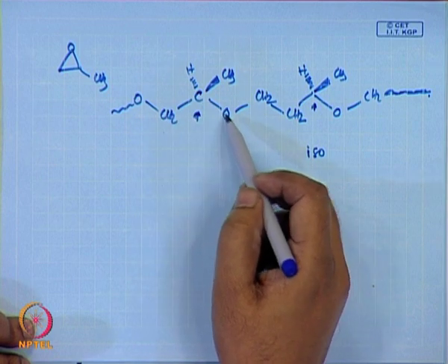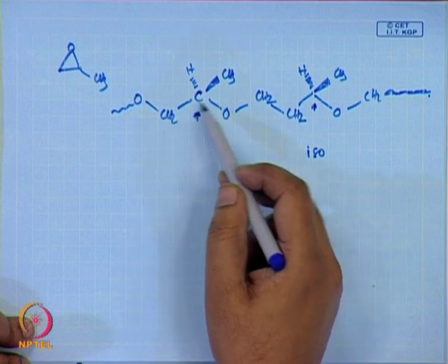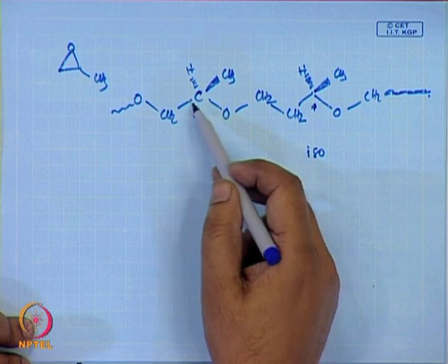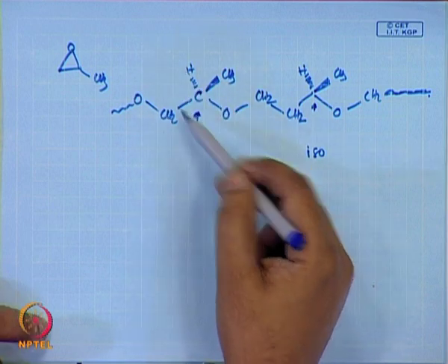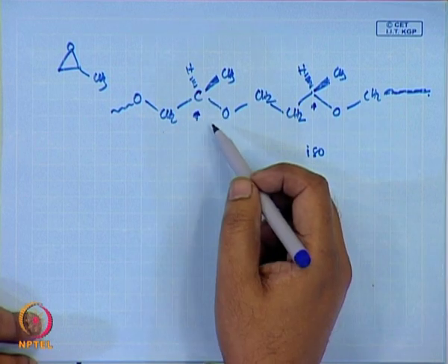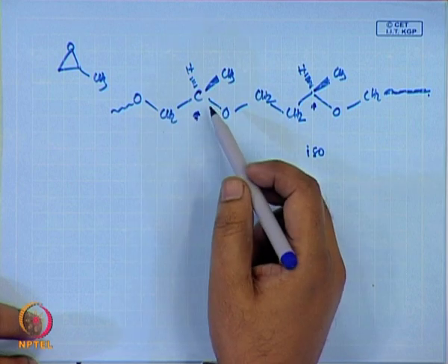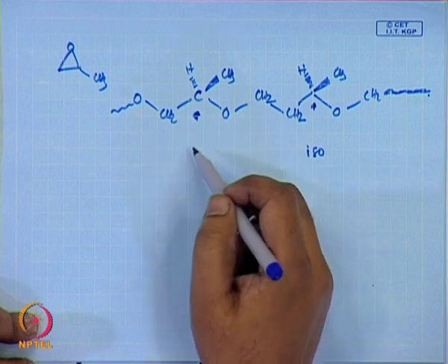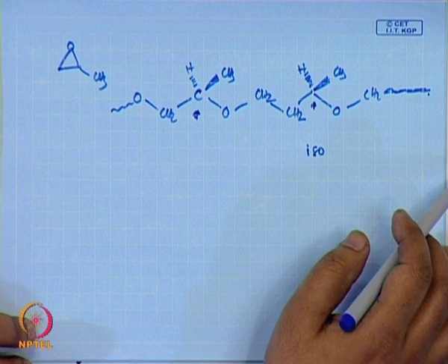Unlike chain polymers with only a carbon backbone, in this case you have oxygen as the next atom on one side, and a CH2 on the other. So, you expect that this will show optical activity, unlike a molecule like polypropylene, and indeed this type of polymer does show optical activity.